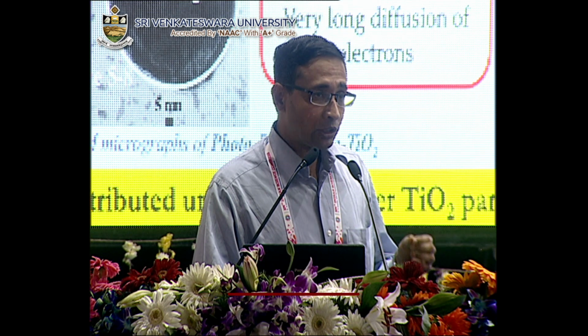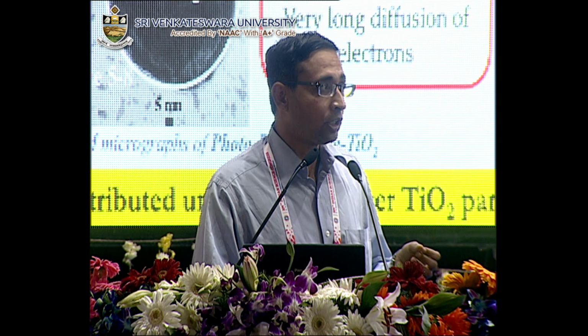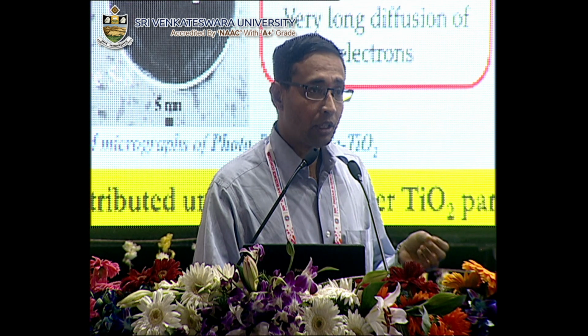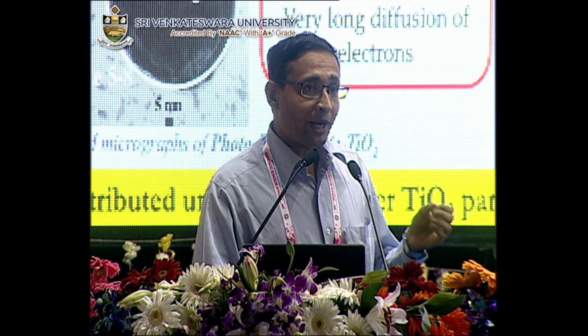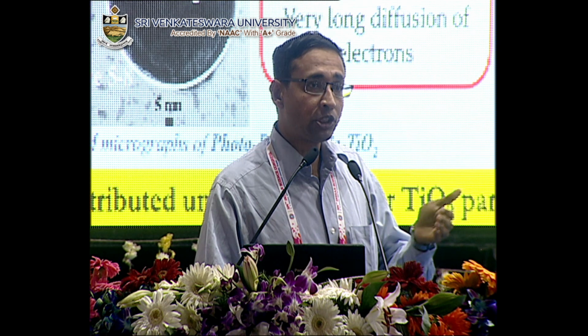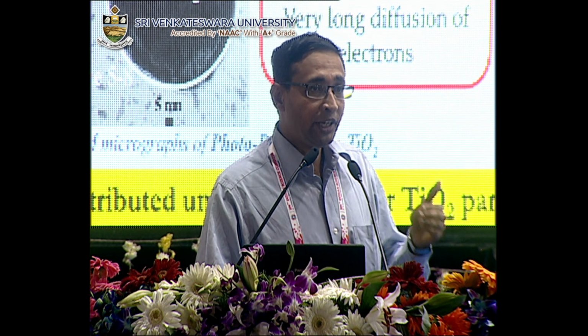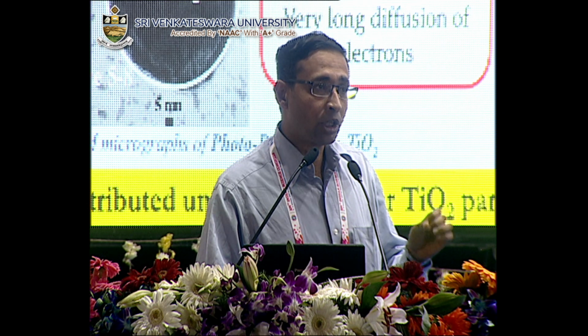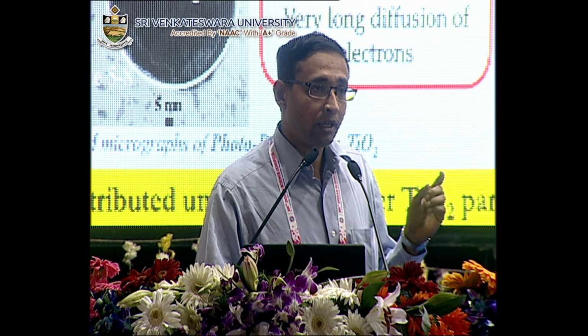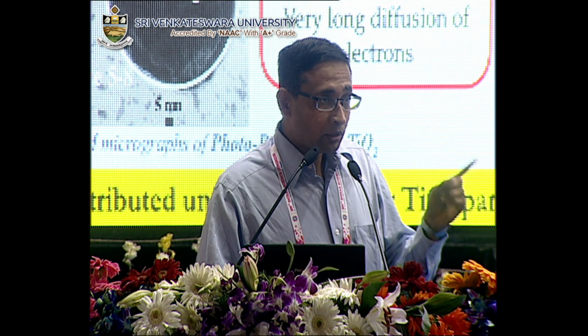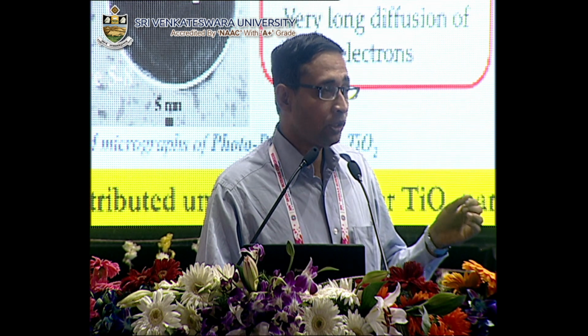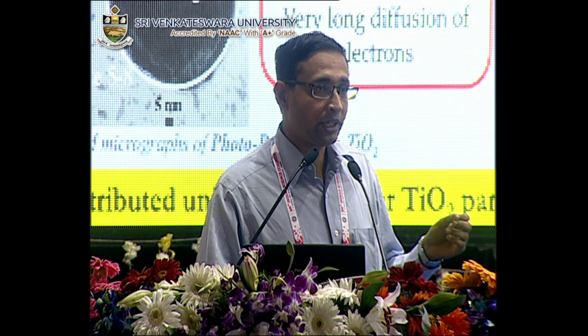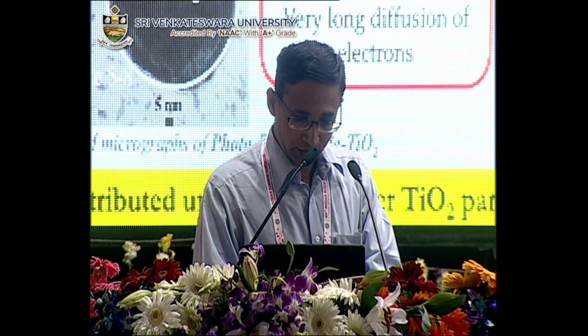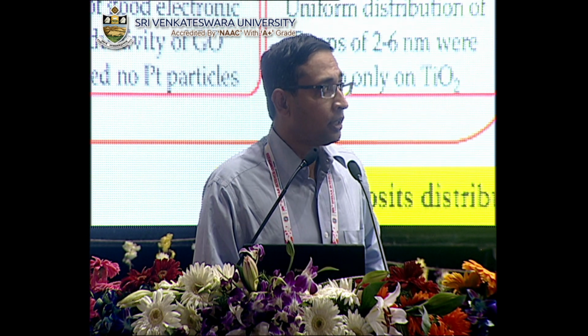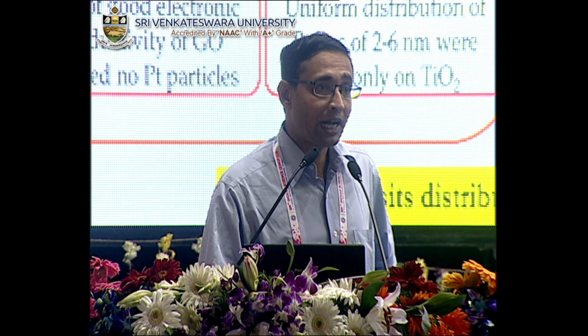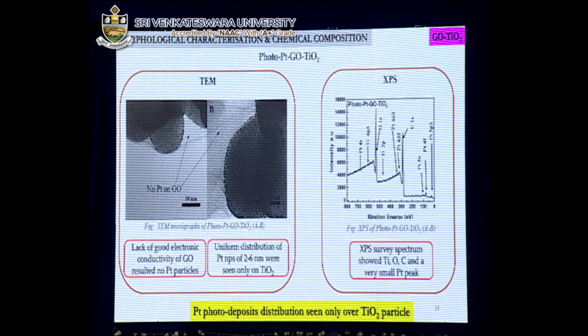And when it was resolved at higher resolution, we found that the platinum was in fact in its native, zero state. That is, platinum can undergo many oxidation states which are not suitable for an electrocatalyst. We need platinum in the zero state, which is suitable for use as an electrocatalyst in a fuel cell. So this high resolution XPS showed that the platinum was in its zero state and can be used as an electrocatalyst. Now, we carried out a similar experiment over graphene oxide, which, as you might know,